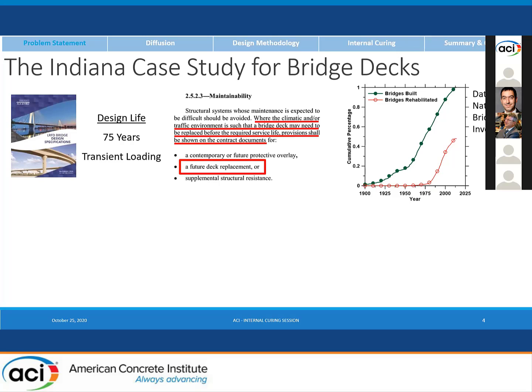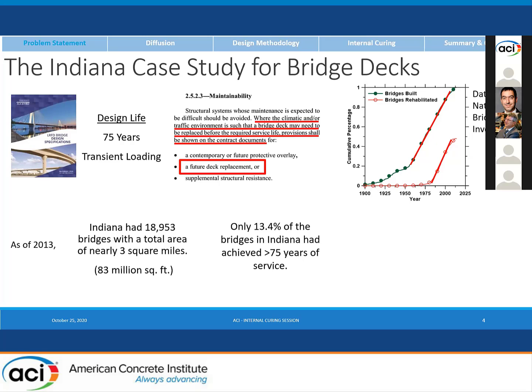And you actually can go through and you can see that this is in fact what we see in the field. So this is data from the National Bridge Inventory for the state of Indiana. And you can see that when we began constructing bridges back in the 50s with the Interstate Highway Program, and you can see a line offset from that, which is the bridges that we're rehabilitating, which includes bridge deck replacements. And there's about a 27-year difference between those two, and indeed that seems to match up quite well with what they're seeing for the performance of those bridges in Indiana. So as of 2013, when I originally did this assessment, there were about 19,000 bridges. Only 13% of them had actually achieved the 75-year service life or greater. The cost estimated in 2013 dollars to replace all of that, $3 billion, give or take.